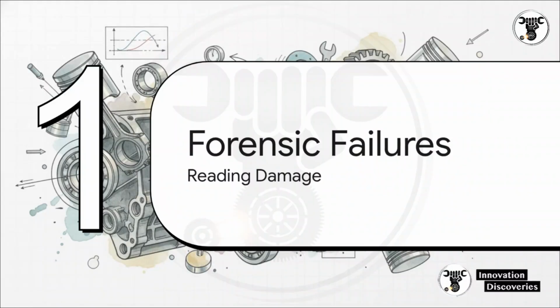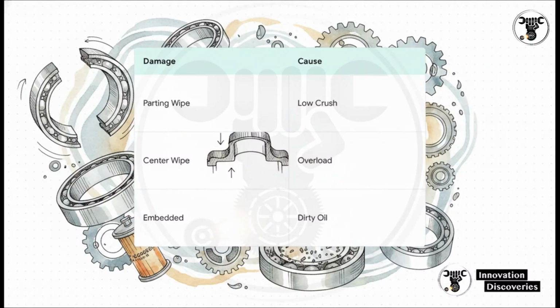Section 5. Reading forensic bearing failures. Let's treat a blown engine like a crime scene for a minute. When you pull these metals out, their damage patterns are literally your forensic map. See heavy wiping concentrated just at the parting faces? That tells you there was insufficient crush. The bearing literally wiggled around in the bore. What about a clean wipe right in the dead center? That's classic overload fatigue. You simply exceeded the hydrodynamic film pressure.